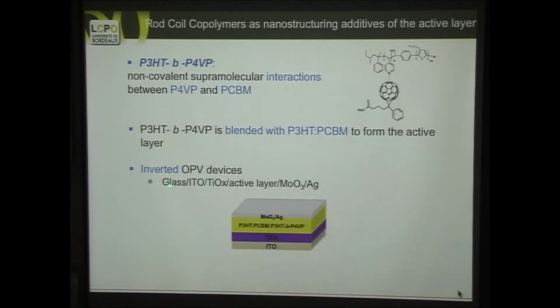So we use the device that we call inverted, for those that are introduced to the system. The normal device will be the indium tin oxide and the active layer. So that means the anode, and this will be the cathode. But in this device, we put, instead of putting PEDOT:PSS here, we put titanium oxide. So we transform the anode to a cathode, and we use molybdenum oxide and silver to have here the anode. And we used this mixture, the formulation of these 3 materials, 2 polymers, a block polymer and a homopolymer, and a particle, acting as the donor acceptor, and a block polymer acting as an additive that will nanostructure again this polymer blend, and also reduce the interfacial tension between the homopolymer phase and the nanoparticle.